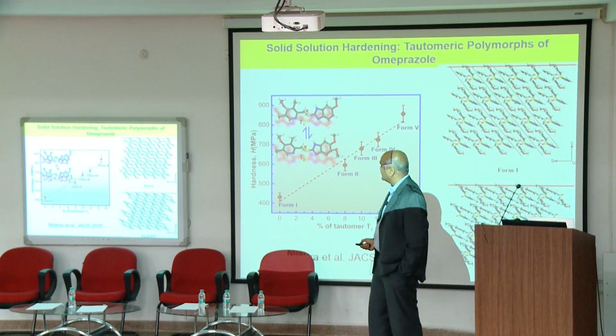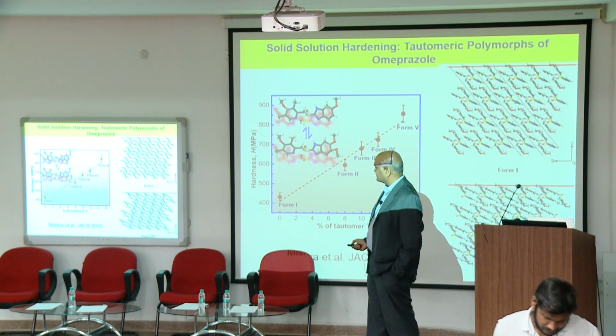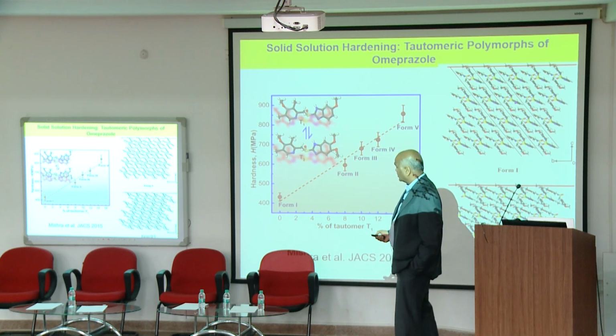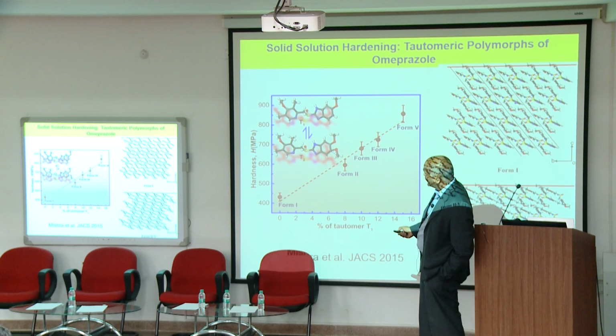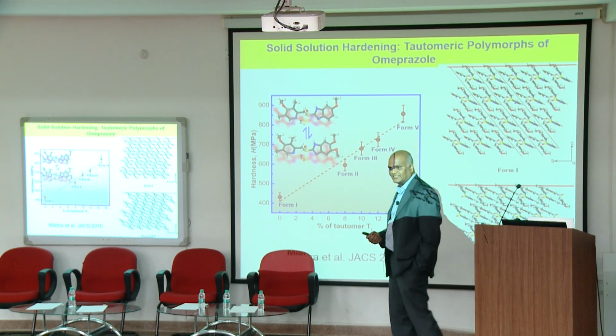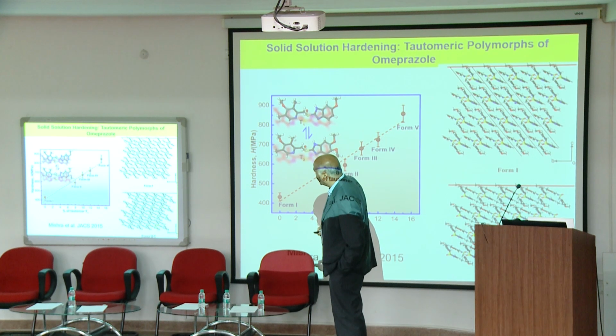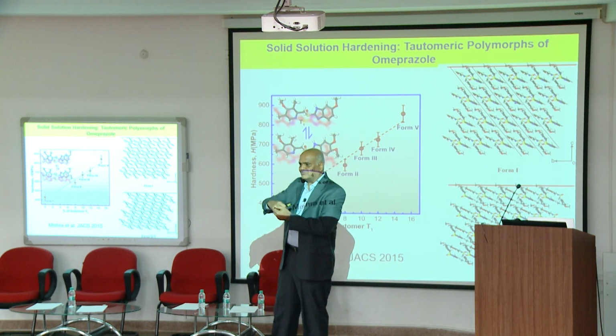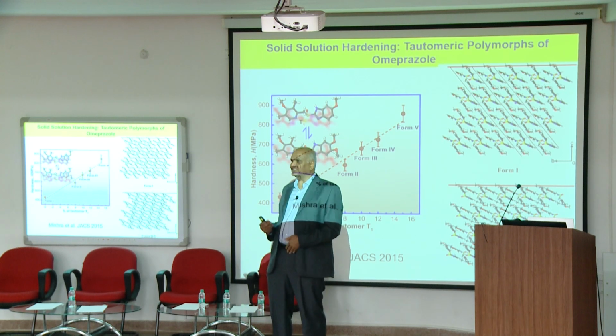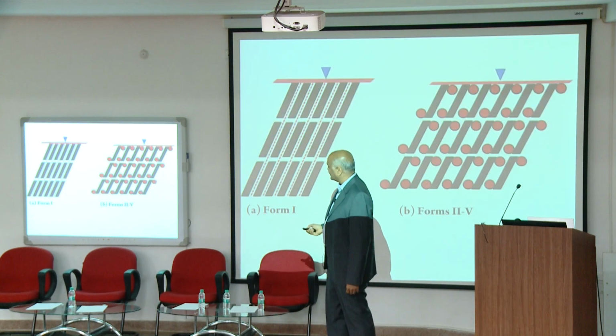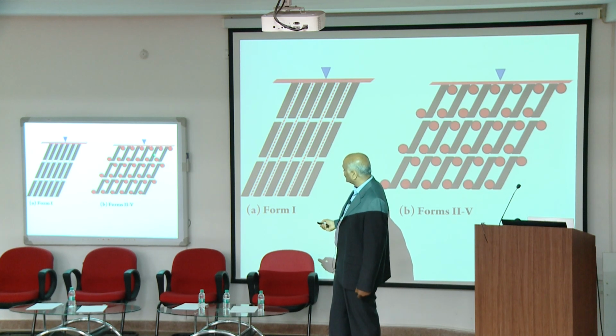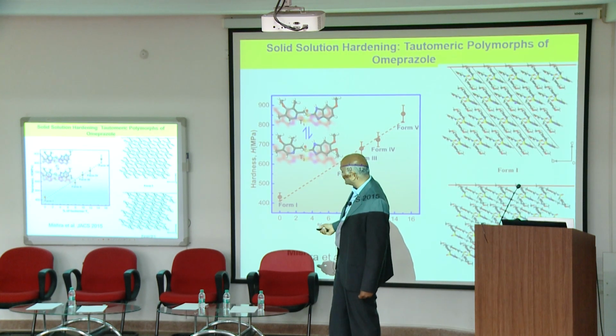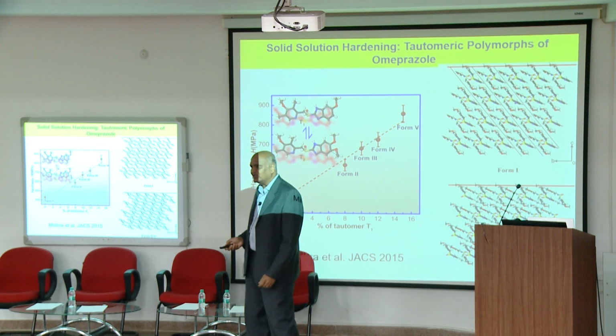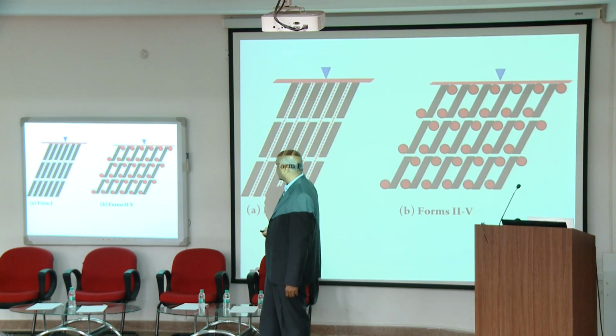Basically it's a tautomer. So by changing the content of the tautomer, you can actually vary the hardness. If I look at form 1, hopefully you see that it is the softest, and I have all these slip planes, so it easily slides past each other, and that's why you get low hardness. But when I go to other forms, they are sort of interlocking, increasing interlocking, and as a result hardness keeps going up. So this is a schematic illustration. Form 1 is like this, and form 2 has these extra things. If you go back and look at the actual crystal structures, you see these red dots. They start to increase in number, and as a result you have this.